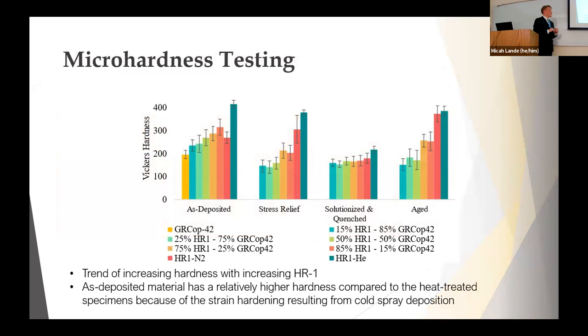So then, starting with some of the mechanical properties, going into the microhardness testing, in each one of the states from left to right. From left to right, we have a pure copper alloy moving over to our HR1, and then in between, we have different ratios of them, 75/25, 50/50, and such. We can see pretty clearly at the start, in our as-deposited state, we have an increasing microhardness with that increasing HR1, which makes sense. It's a significantly stronger material. It's not as soft as copper, so that fits with exactly what we imagine it to be.